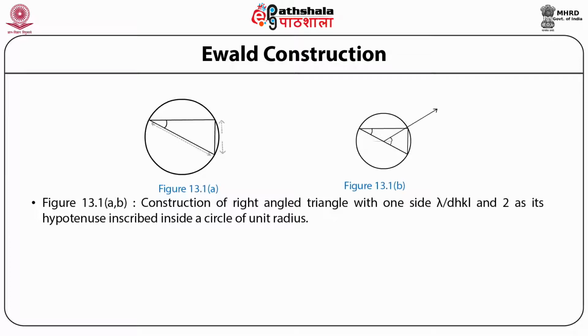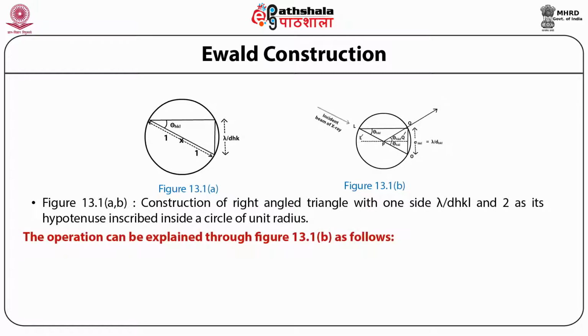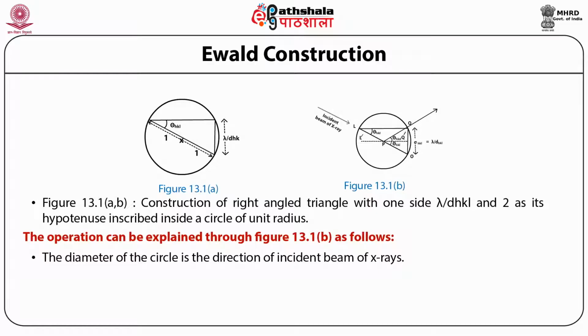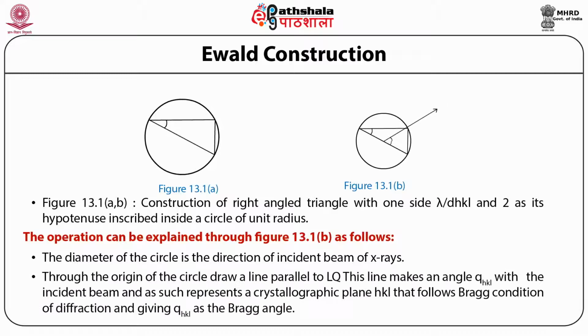Figure 13.1a shows a construction of a right-angled triangle with one side lambda by dHKL and 2 as its hypotenuse inscribed inside a circle of unit radius. The operation can be explained through figure 13.1b as follows. The diameter of the circle is the direction of the incident beam of X-rays. Through the origin of the circle, draw a line parallel to LQ. This line makes an angle theta HKL with the incident beam, and as such it represents a crystallographic plane HKL that follows Bragg condition of diffraction, giving theta HKL as the Bragg angle.